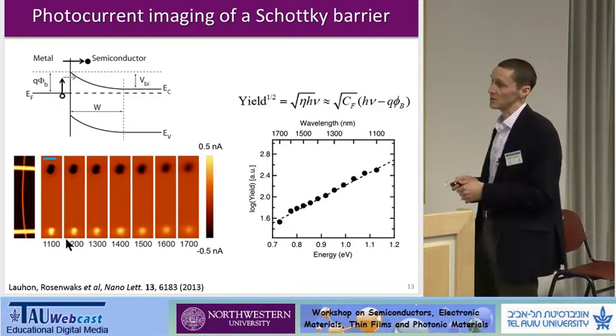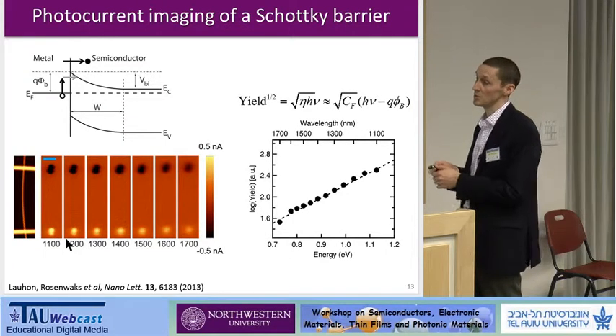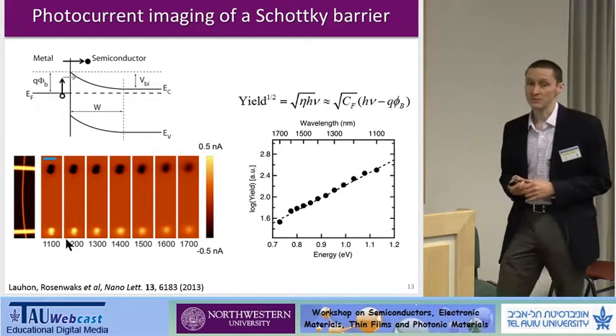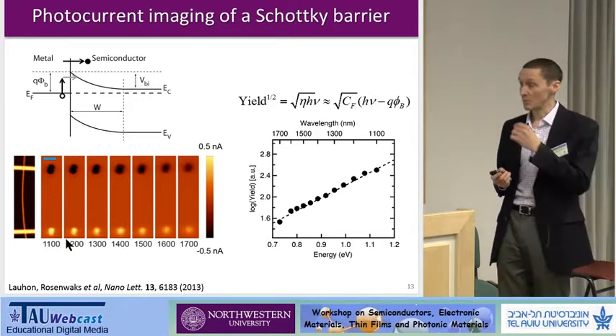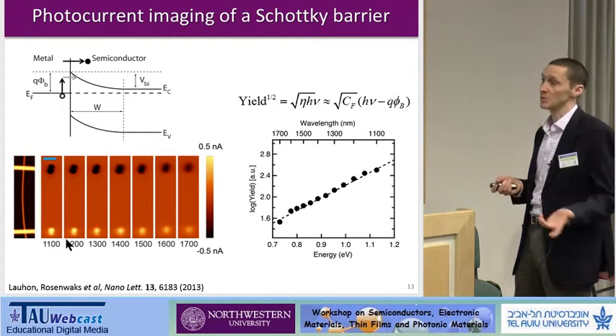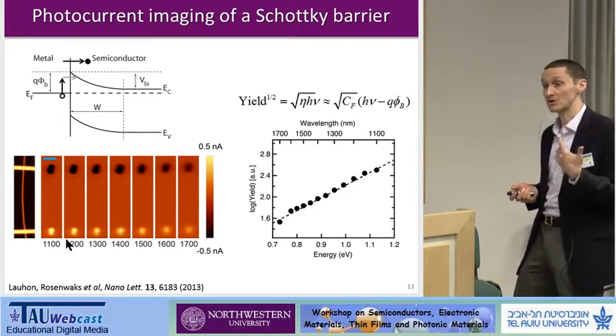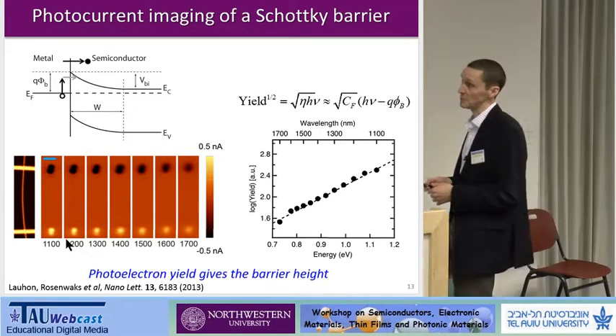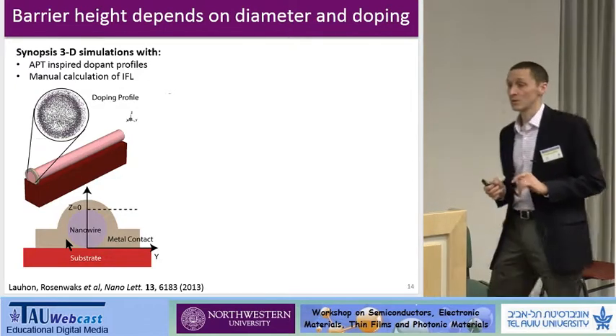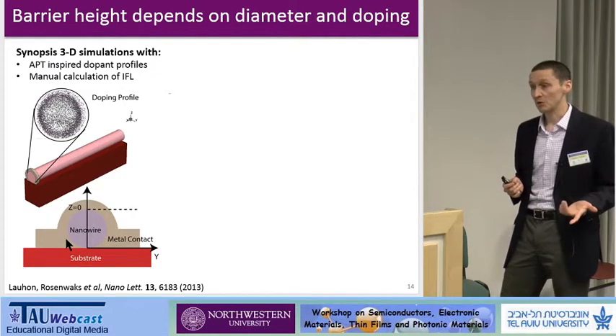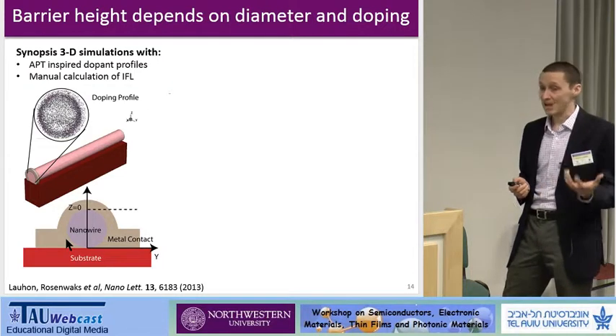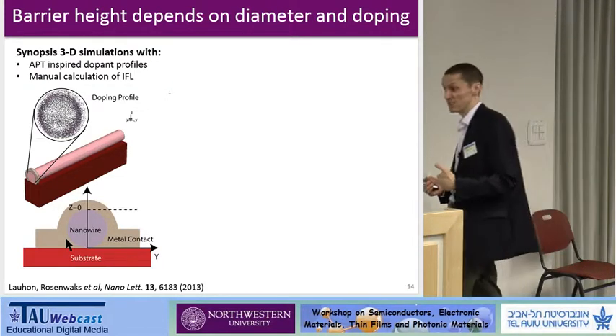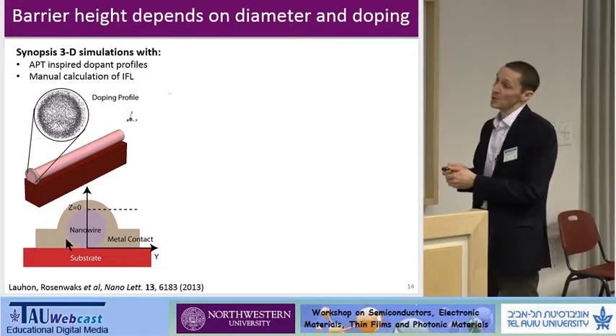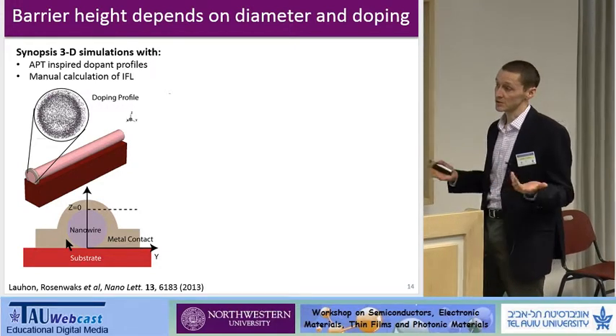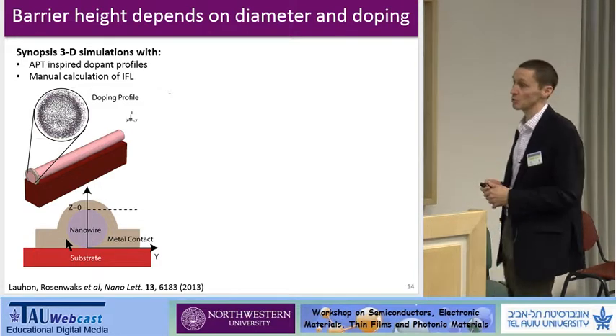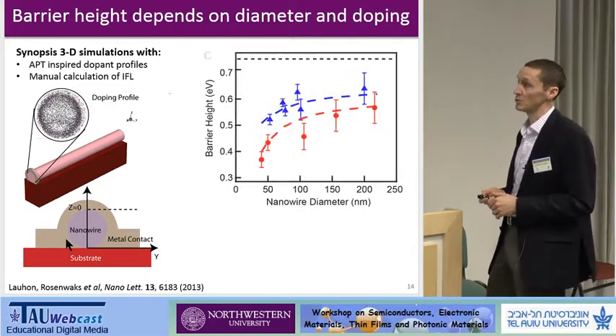Quantitatively, if we extract that dependence, we see that the yield, or the square root of the yield, depends on energy, as one would expect for a Fowler model of internal photoemission over that barrier. So this fit essentially enables us to extract the Schottky barrier, which, as I mentioned, is dopant concentration dependent. Okay. And so taking into account what we measure in atom probe, and Yossi's measurements of the active dopant concentration, which turns out to be much less than the physical dopant concentration, we input that into a device model, Sentaurus, to calculate these potential profiles and see how they match up with the photoemission measurements.